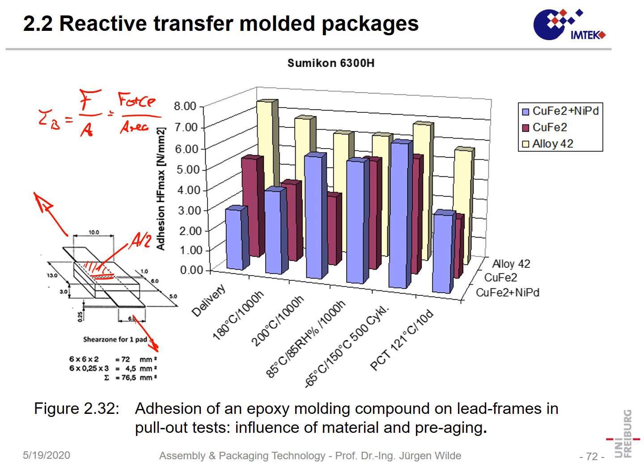So that's the strength after we just do the molding. Another question is, how will that behave after a certain time of operation? And here on this x-axis, we see different environmental tests we do. For instance, one test would be keep it at 180 degrees centigrade for 1,000 hours. What we can see here is the strength on copper iron 2 with nickel palladium will increase a little. The strength of copper iron will decrease. It's a similar behavior at 200 degrees centigrade. On the alloy 42, not very much will happen. That decrease is mainly a result of copper oxidation.